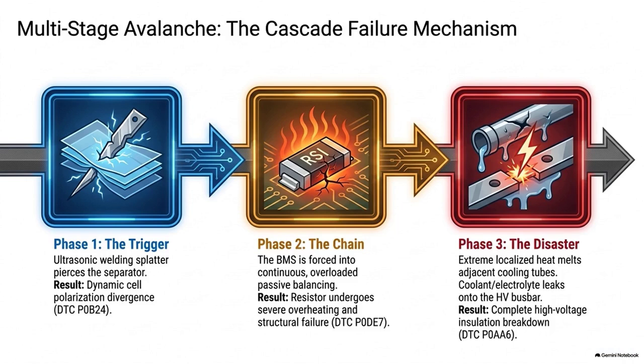Because the rest of the pack is at a lower state of charge, so the car is still requesting maximum current from the charger. Right, but this one unbalanced cell is already sitting right at its upper voltage threshold. So when that surge of current hits, its voltage just spikes dramatically. And when a ternary lithium cell, like a nickel manganese cobalt chemistry, blows past its upper limit, which is what, like 4.2 or 4.3 volts? Yeah, right around there, depending on the exact chemistry.